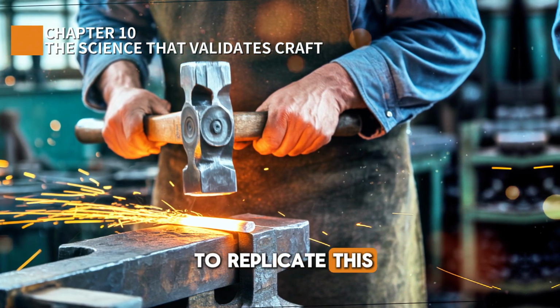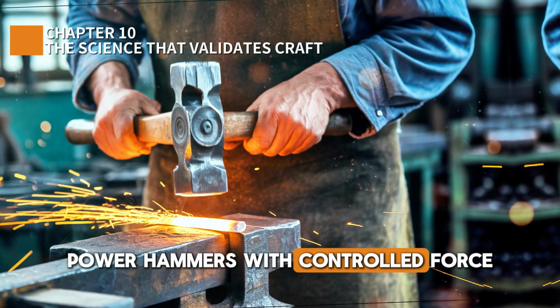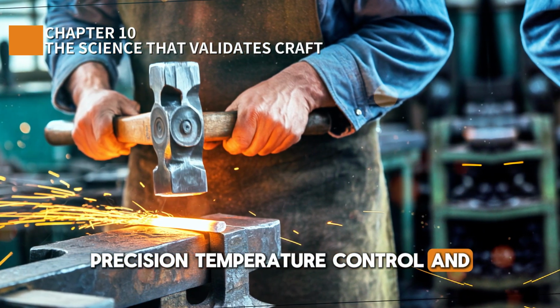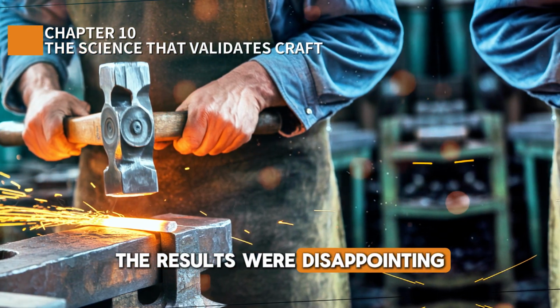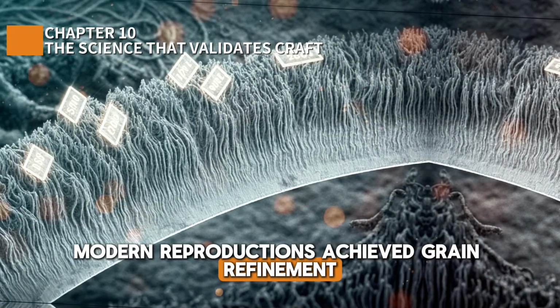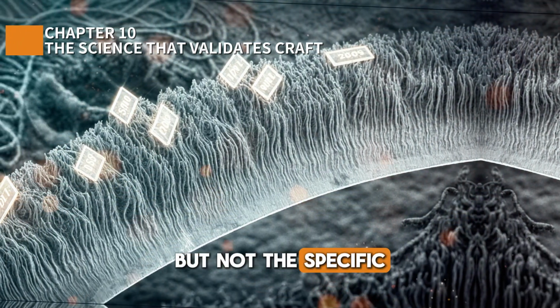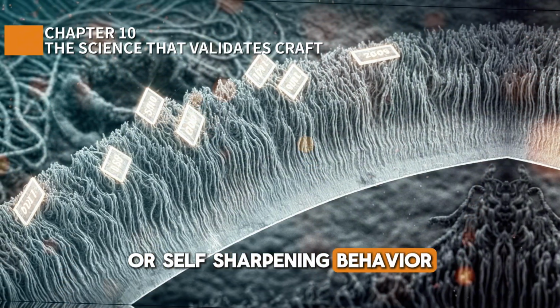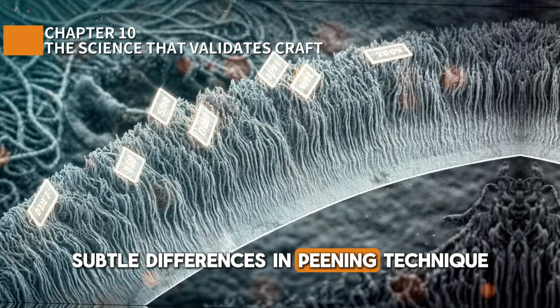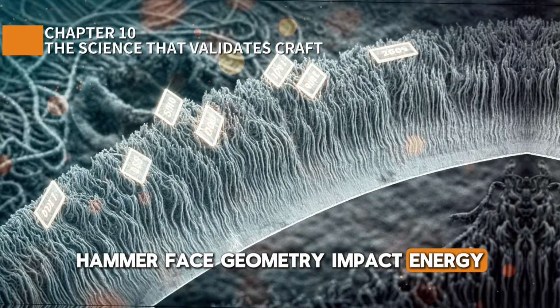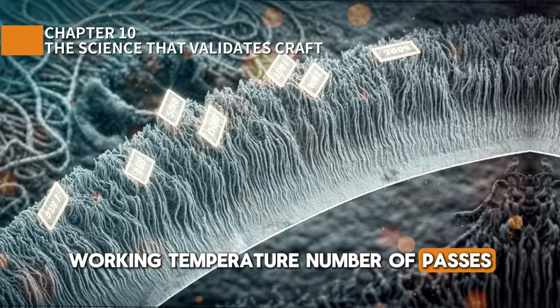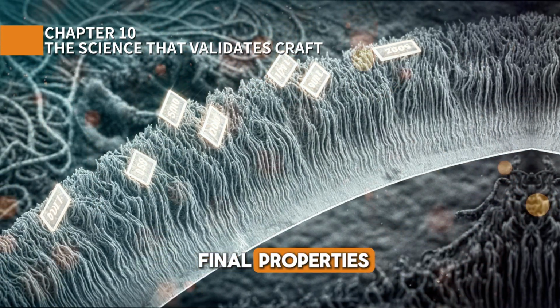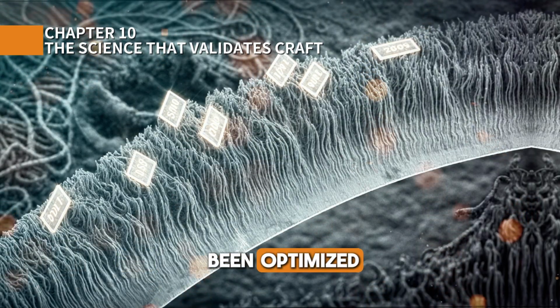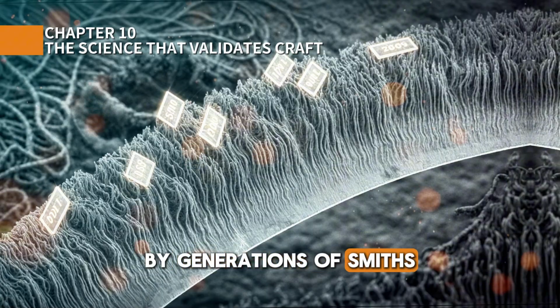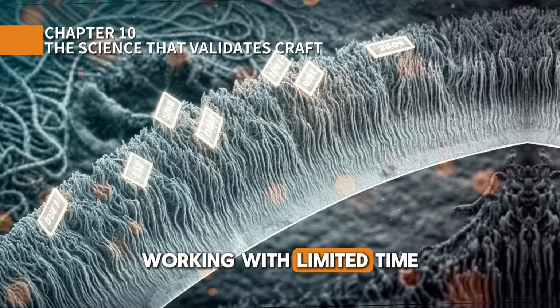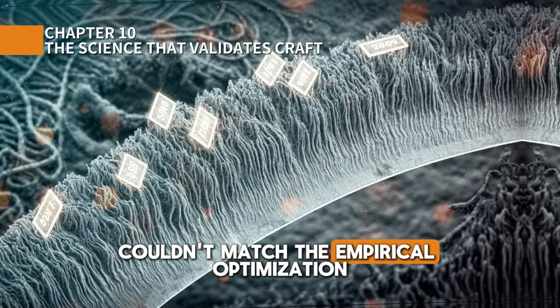Researchers attempted to replicate this using modern equipment, power hammers with controlled force, precision temperature control, and advanced steel alloys. The results were disappointing. Modern reproductions achieved grain refinement and hardness increase, but not the specific gradient structure or self-sharpening behavior of historical blades. Subtle differences in peening technique, hammer face geometry, impact energy, working temperature, and number of passes created dramatic differences in final properties. The traditional technique had been optimized through countless iterations by generations of smiths. Modern researchers, working with limited time and attempts, couldn't match the empirical optimization.